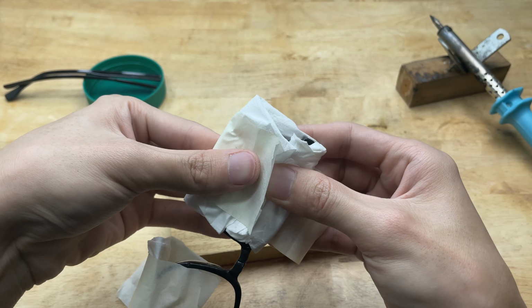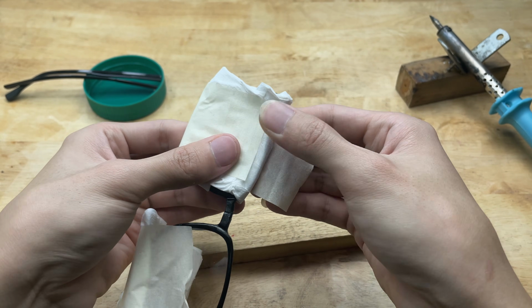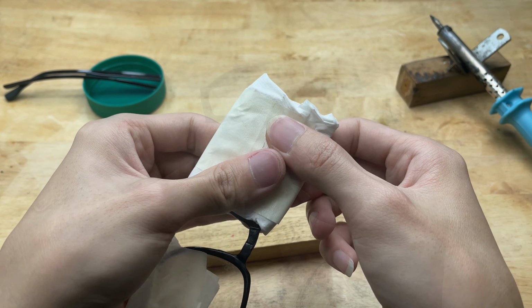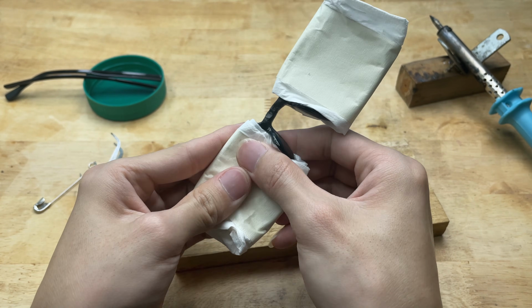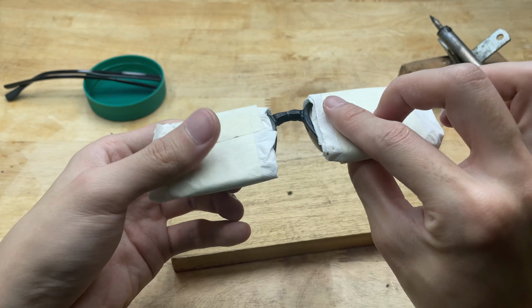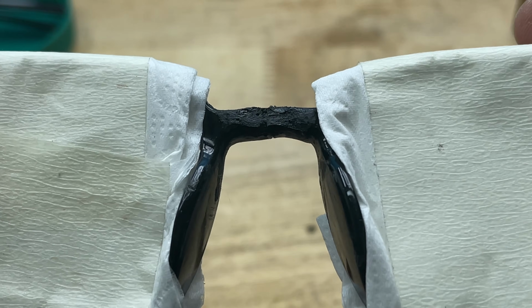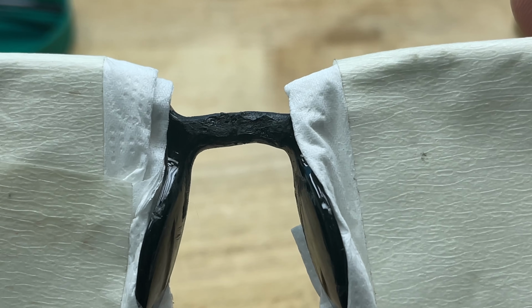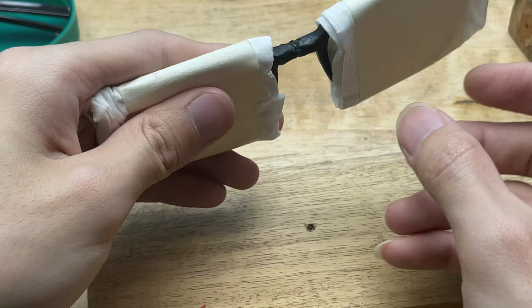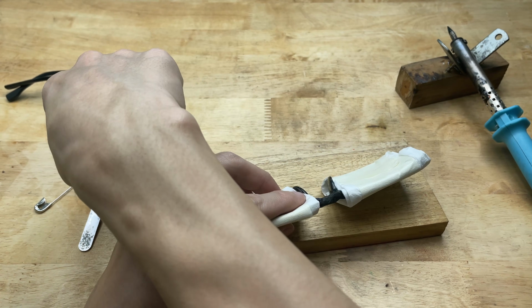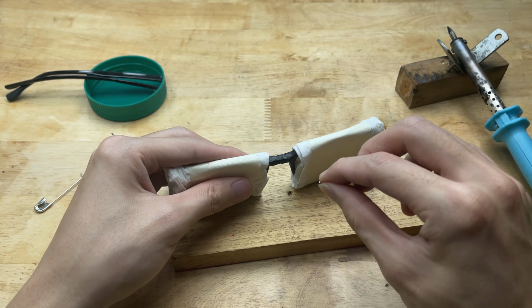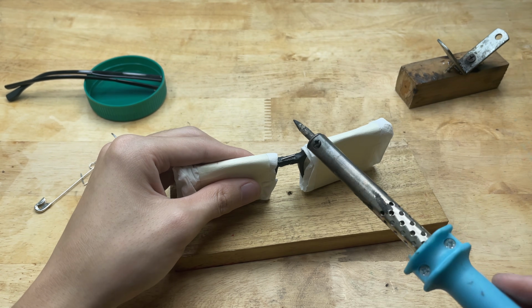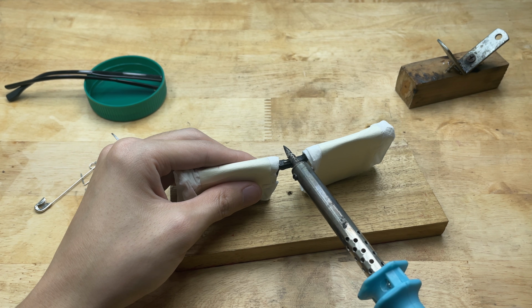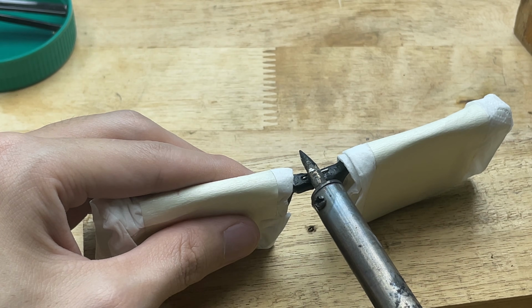After the metal pieces are embedded into the plastic, the structure of the bridge now works similarly to reinforced concrete. The melted plastic acts like the outer concrete layer, while the metal pieces inside function like steel reinforcement that improves strength and load resistance. As a result, the previously broken area is not only rejoined but also becomes much sturdier and more stable compared to a simple glue repair.